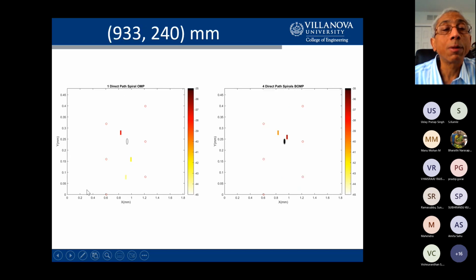Another example where the single path fails, that's your defect, but your predictions are everywhere else. And here's a case where there's your defect, and you identified where the defect is pretty well. Notice how you have 3 predictions over here. So that's the thing that sparse reconstruction allows you. I mean, a priori, you're not going to know how many defects you have in your structure. Now, we just happen to know how many defects we have because we put them in. But in practice, you're not going to know how many defects there are in your structure. There could be 1, there could be 2, there could be 3. And so in sparse reconstruction, what you do is you can decide how many defects you want to look for. And so you can say, well, I'm assuming there are 3 defects. Tell me where they could be. And so that's kind of what we've done here.